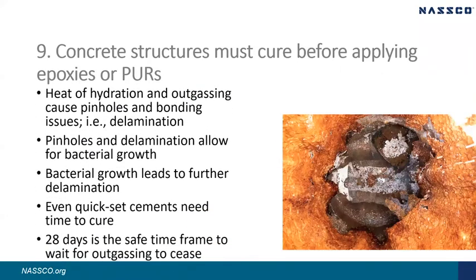Point 9. If a wet well or a manhole has been recently installed, it is necessary for the structure to cure before protecting it with level C polymer resins. This is due to the heat of hydration and outgassing common to curing concrete. While the desire to complete the project quickly is important, it is necessary for long-term reliability to wait at least 28 days before applying the polymer resin. If not, delamination and bonding issues will ensue.